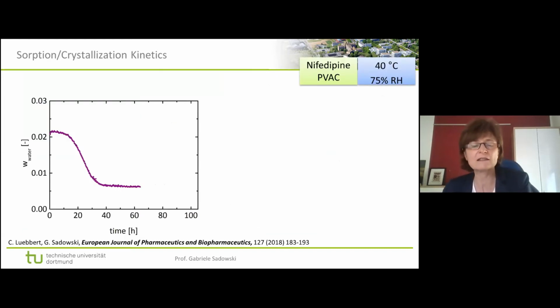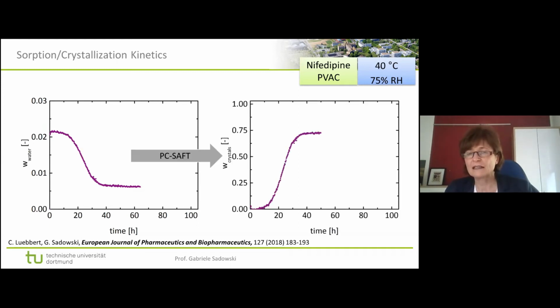So what we did is, we took this absorption curve and recalculated it, because we can calculate how much water is absorbed in a fully amorphous sample. We can also calculate how much water is in the fully crystallized sample. Fully crystallized meaning every API that wants to crystallize is crystallized. We can calculate how much water this sample will absorb, and we proved that what we do is correct. And that means that we can do the same thing for every point in between. So we can translate, by using a model, this water uptake curve into a crystallization kinetic curve.